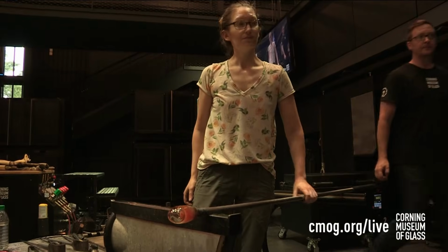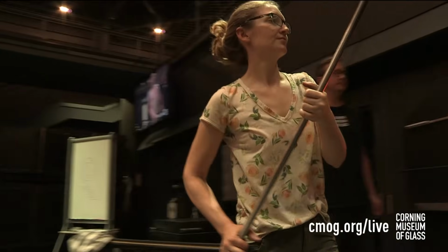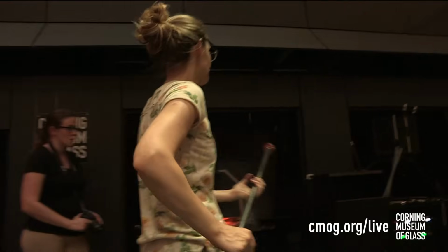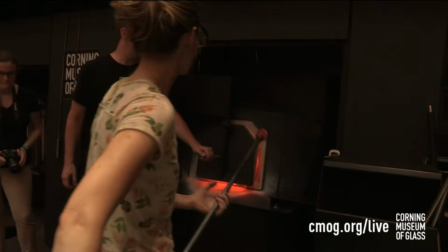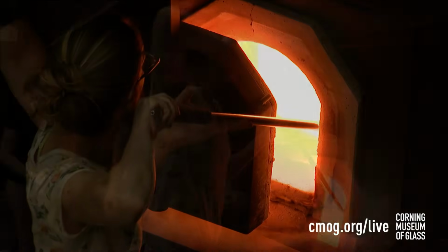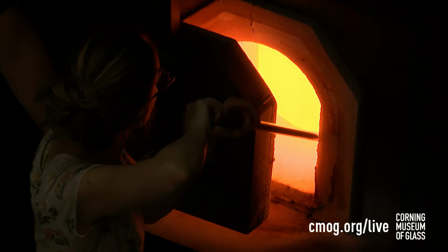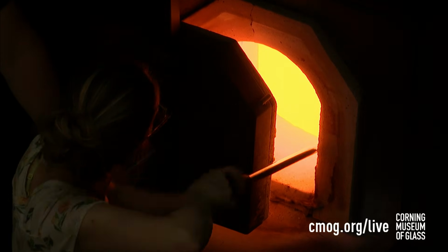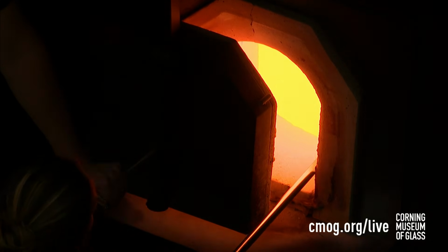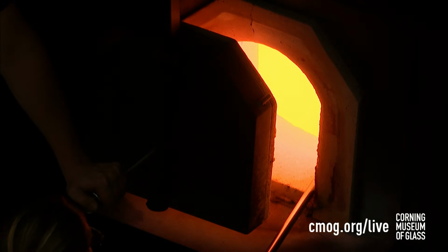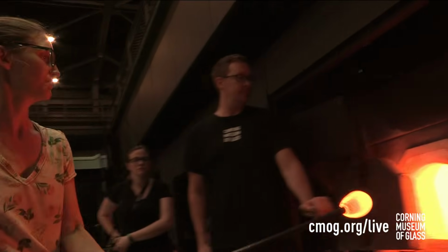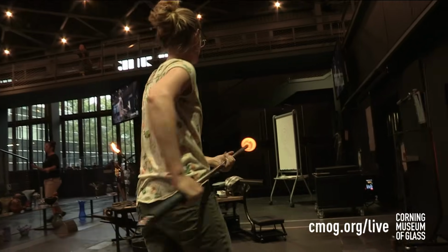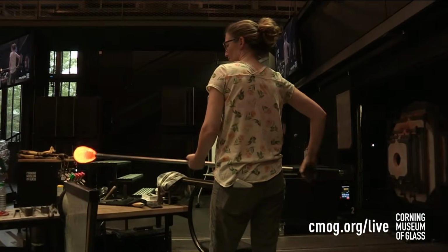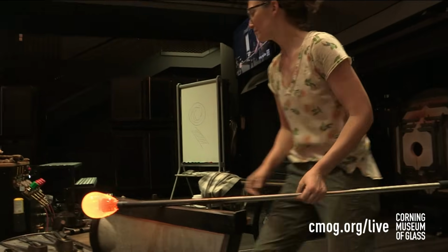We're going to go through a process of gathering again, collecting more and more material. You can only collect a finite amount of material on every gather. And there is a reason we keep the furnace at 2100 degrees. If it was at, say, 2300 or 2500 degrees, the glass would actually flow closer to water. We wouldn't be able to collect enough material on the end of our blowpipe for each gather.